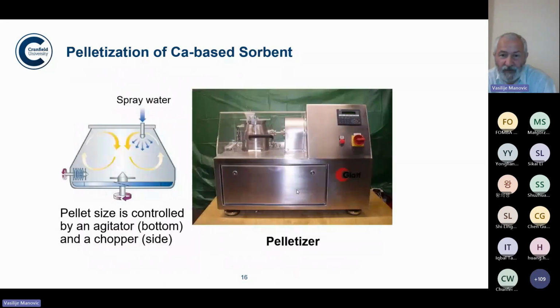We started producing this material in a kind of mechanical pelletizer, and how it looks you can see in this photo and in this schematic representation of the process. So we have this vessel, we add material which we would like to reactivate and to pelletize. We have blades, one at the bottom and one on the side wall. We can control the speed of rotation of these blades. We can control how much water we are adding, and by those parameters we were able, for example, to control the particle size of the material that we were producing. Particle size of pellets is important if you have fluid bed systems.